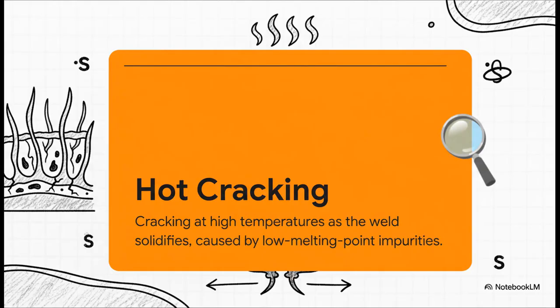Another major enemy is hot cracking, and as the name implies, this happens while the weld is still screaming hot and solidifying. If you have impurities like sulfur in the metal, they get pushed to the very last pockets of liquid between the brand new grains. And these liquid films, they're like wet tissue paper. They have zero strength, and they get pulled apart by the shrinkage of the cooling weld, creating a crack just as the joint is being born.